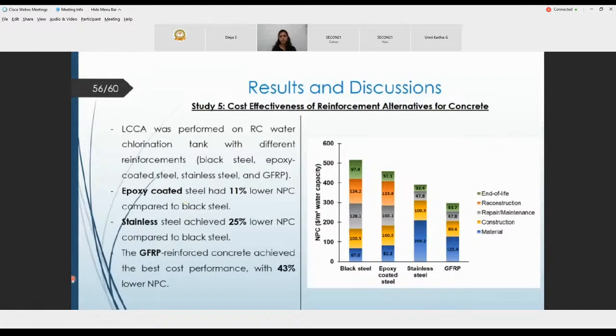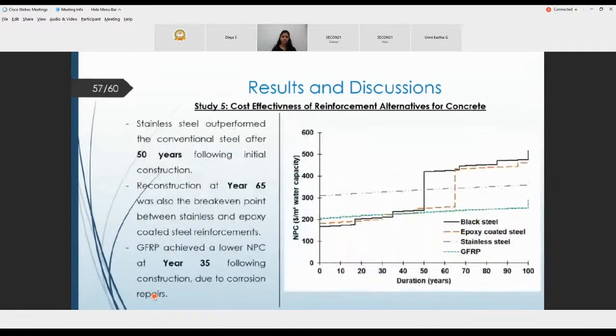The epoxy coated steel alternative had 11% lower NPC compared to black steel. Stainless steel achieved 25% lower NPC compared to black steel. The GFRP reinforced concrete achieved the best cost performance with 43% lower NPC. Stainless steel outperformed the conventional steel after 50 years following initial construction.